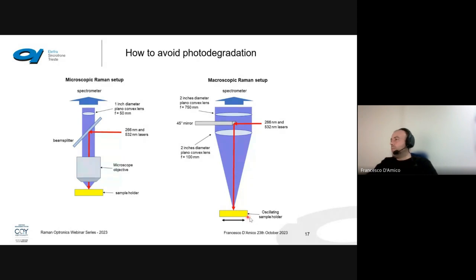On a macroscopic Raman setup it is easier, also because we have a higher focal length, and we can oscillate the sample, for example, to avoid photodegradation. We can move the sample and make measurements on a homogeneous sample, avoiding photodegradation.